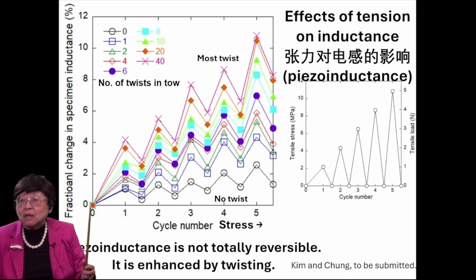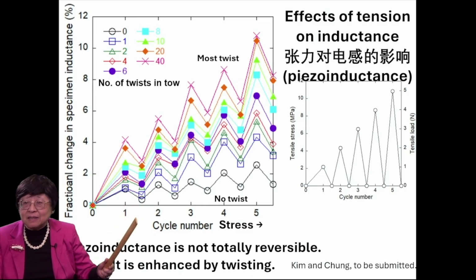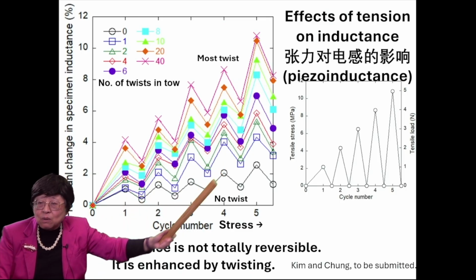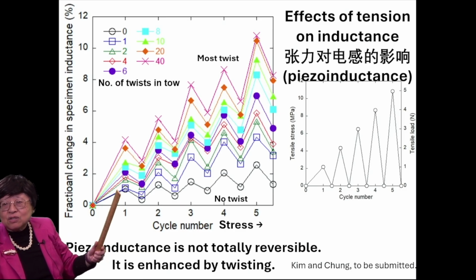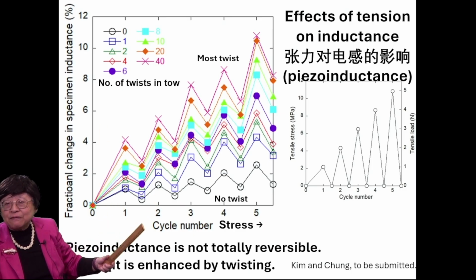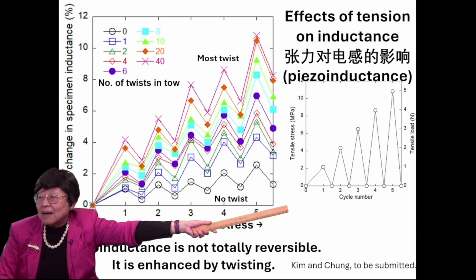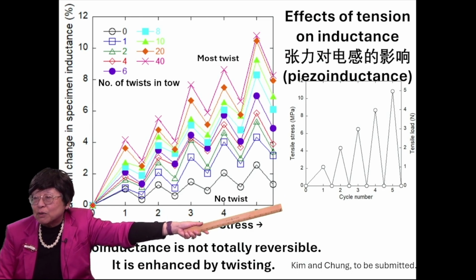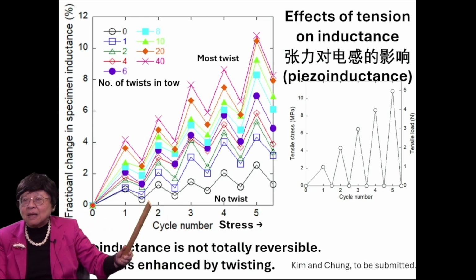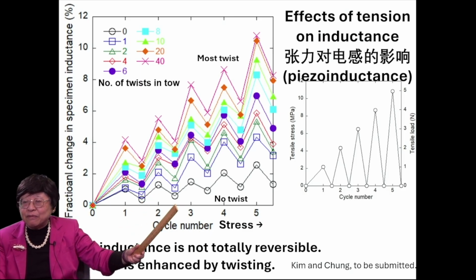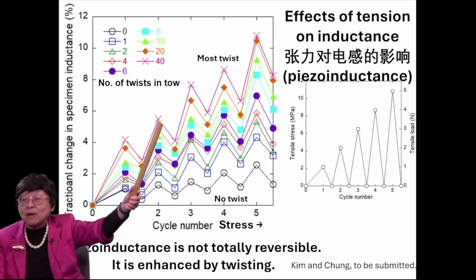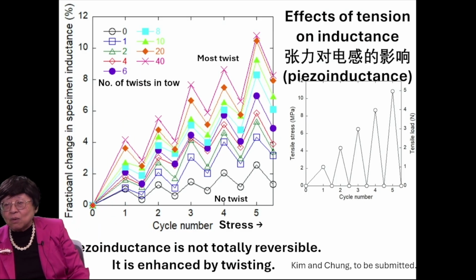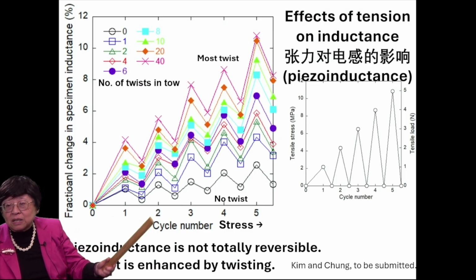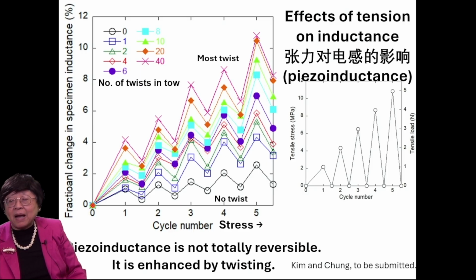Tension on the tow also affects the inductance, and this is called piezoinductance, and this shows the effect of cyclic tension. Okay, here, 5 cycles at progressively increasing stress amplitude, and the inductance increases every time you stress it, and the effect becomes bigger and bigger as you have more and more twists. Okay, so the piezoinductance is not totally reversible, but is enhanced by twisting.